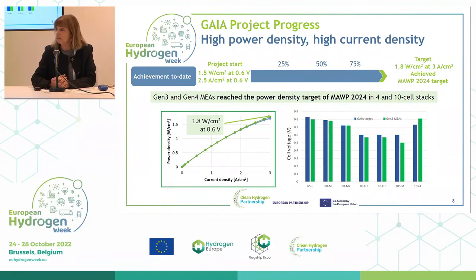300 square centimetre cells and 4 and 10-cell stacks. What we had during the course of this testing was 7 operation points, at different loads and different temperatures, and the blue lines there are the target, and the green ones what was obtained with these GAIA 4th generation MEAs, and in most of the cases the target cell voltage was actually achieved.